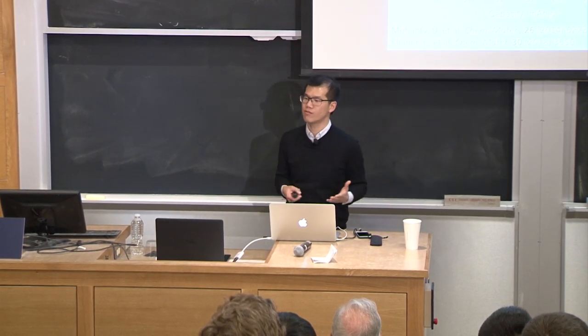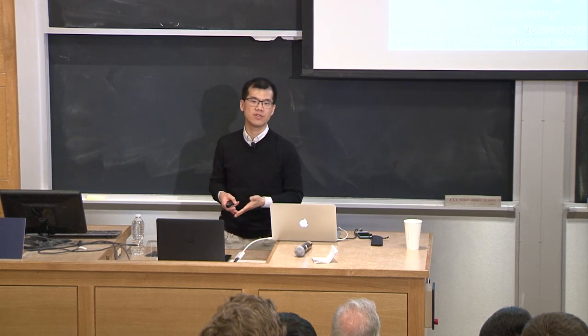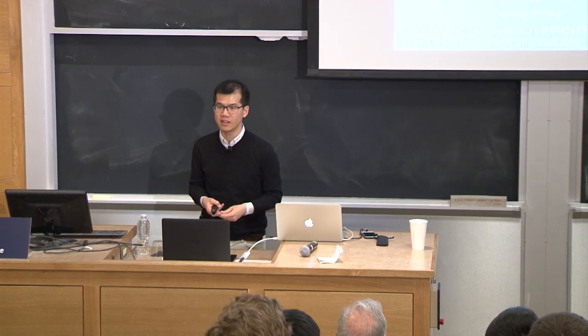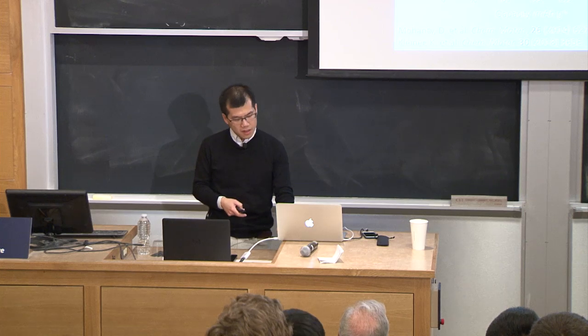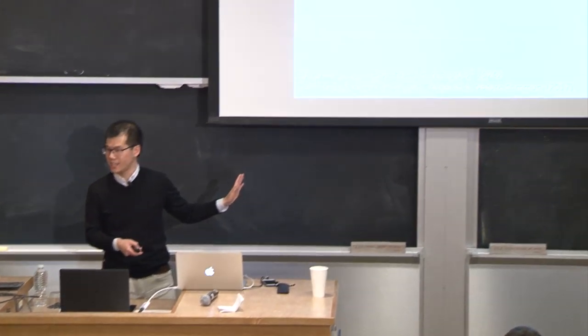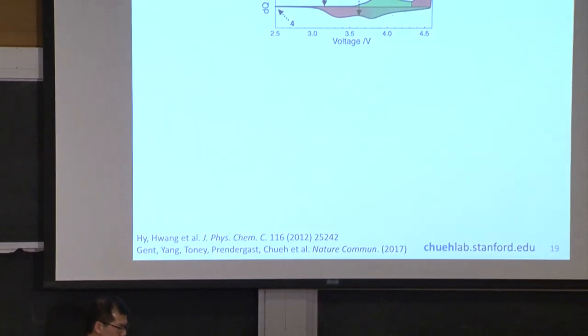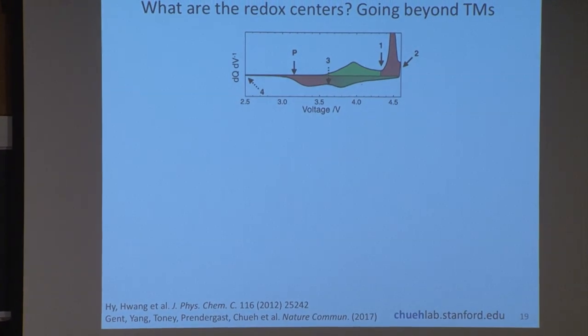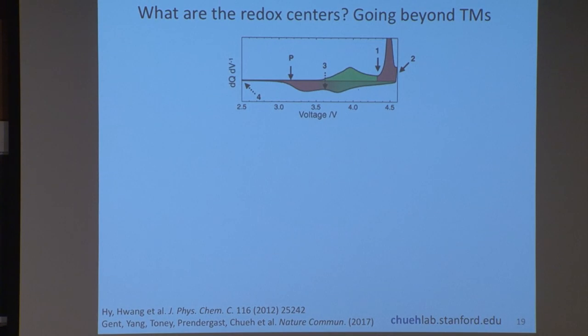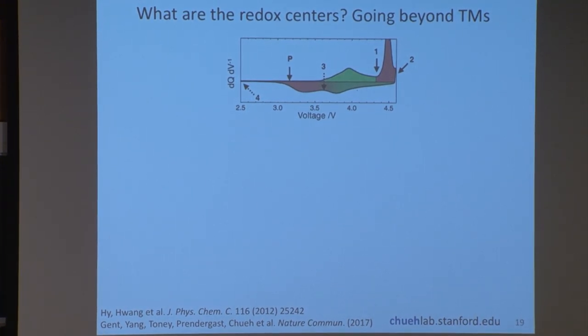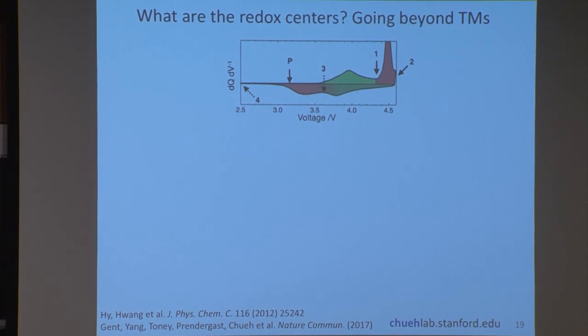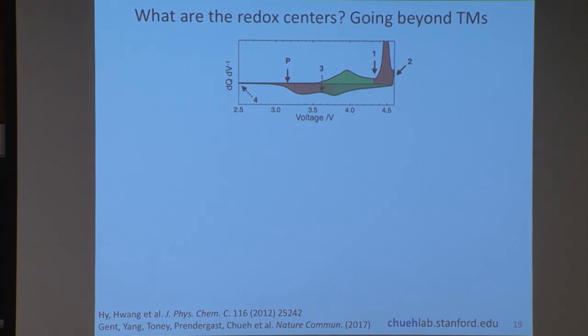So what can we understand from this? This is what I would consider the science of degradation in the system. I'll give you one technical slide here, a little bit more in depth. The question we have to ask is, we are removing electrons from oxygen, which is not bonded to anything. In principle, this is very bad for any oxide. But yet this material can continue to operate for many hundreds of cycles.